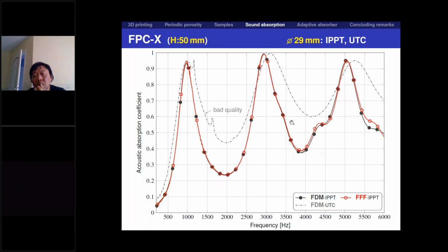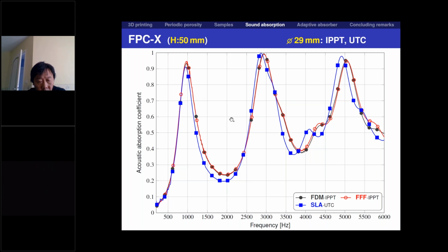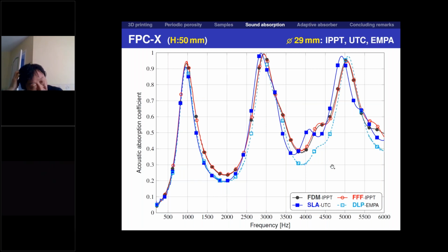Okay, so then I got the results from France, and first I compared the results for the FDM sample, and I was quite unhappy to see that we have such large discrepancies. But then I looked at the photographs, and I realized that there are these small fibers which increase the sound absorption, especially between the peaks. The first peak is well represented, but the other peaks are not so well represented, and there is a much larger absorption between the peaks. So this is because of the very bad quality of the samples. But then when I looked at the curve for the samples manufactured from this black resin, it appeared that the curves are very similar to my curves. So they were very nice samples, much smoother than mine, but it was not very important, it appears. And finally, I got some results from Switzerland, also resin samples, very similar curve.